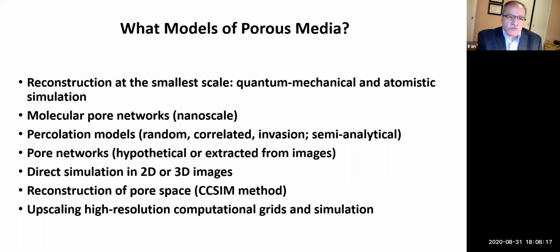When I was a graduate student, I started with random percolation. Then later on, inspired by the observation made by Tom Hewett and others, that porosity and permeability fields in large scale porous media are actually quite correlated, I developed a correlated percolation. And then invasion percolation that others developed, but together with collaborators in Australia, we made it very efficient, and therefore it is very good to use now.